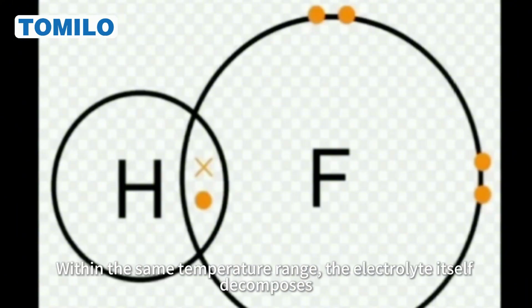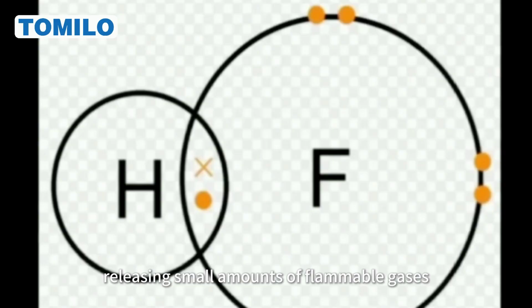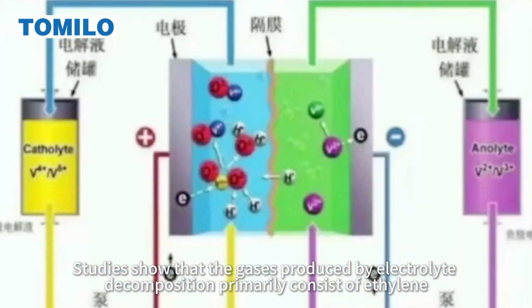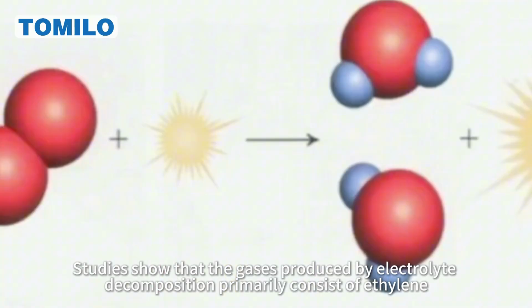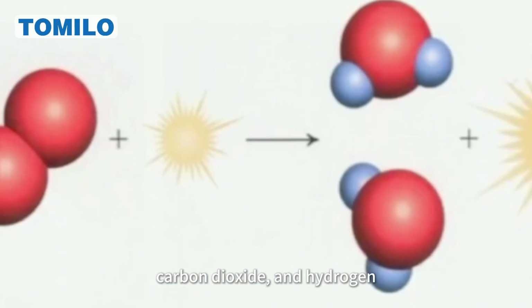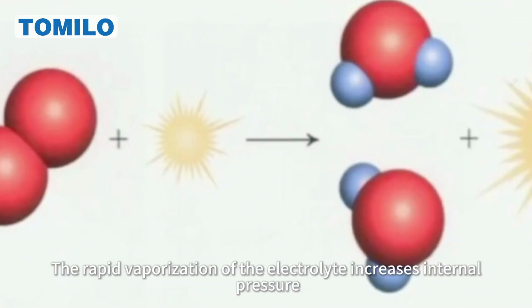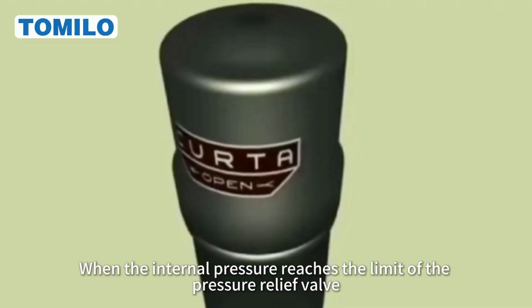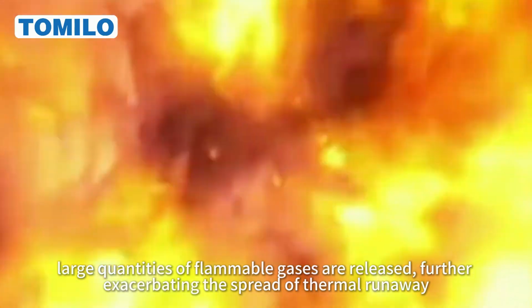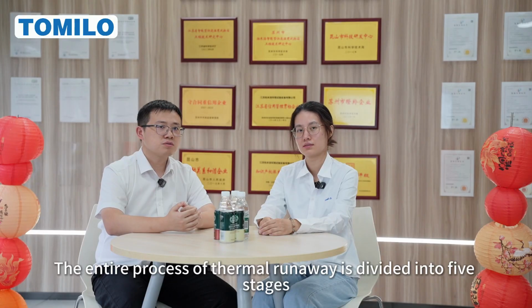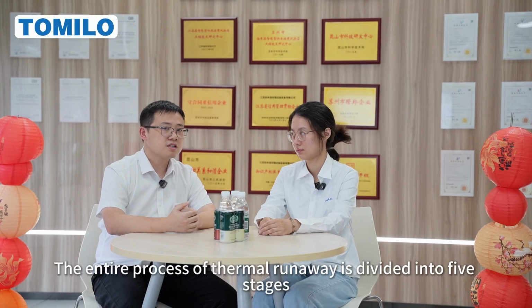Within the same temperature range, the electrolyte itself decomposes, releasing small amounts of flammable gases. Studies show that the gases produced by electrolyte decomposition primarily consist of ethylene, carbon dioxide, and hydrogen. The rapid vaporization of the electrolyte increases internal pressure. When the internal pressure reaches the limit of the pressure relief valve, large quantities of flammable gases are released, further exacerbating the spread of thermal runaway. The entire process of thermal runaway is divided into 5 stages.